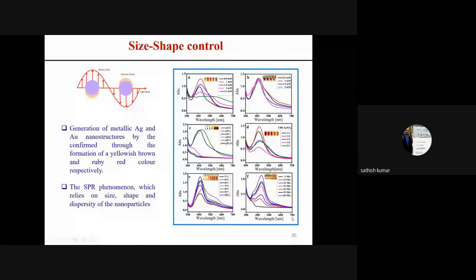So in this UV visible spectrum, the broad spectrum clearly indicates the polydispersity of the nanoparticles, whereas the intense peak clearly indicates the presence of monodispersed nanoparticles, which means the particles are in a narrow size range. For example, 5 to 10 nanometer, 5 to 15 nanometer. Whereas the broad spectrum indicates that the particles are polydispersed in nature, which means the particles are in a 10 to 60 nanometer, 10 to 80 nanometer range. So based on this SPR peak, we can predict the size and shape of the nanoparticle, as well as we can optimize all the reaction conditions like pH, temperature, and the incubation time also.